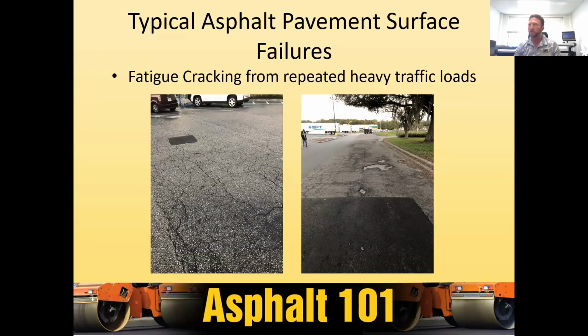This is a structural failure, and this isn't a surface that can just be milled partial depth and overlaid. Again, asphalt's only as strong as the material that you're putting it on top of. So if you've got a nice sturdy foundation, a solid base, or a nice structurally performing asphalt, you can cap that with more asphalt and you'll be just fine. If you've got a structurally failed base, such as a fatigue crack or a high severity failure like this, and you just put asphalt over the top of it or even mill portions of it, you're going to see those failures reflected through. Okay. It's very important that we address this from a full depth or structural perspective before we go in and make any new overlays or improvements.